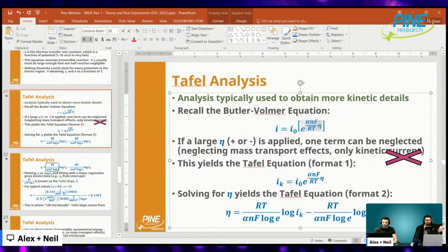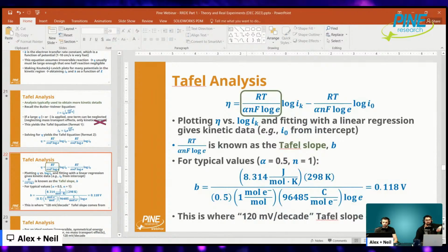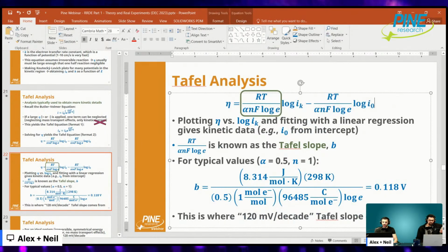Just do a manipulation, take the natural log of both sides, or the log base 10 of both sides, and we solve for eta, and then we get what's known as the Tafel equation, where we can get the Tafel slope. The Tafel slope is all of this stuff in the green box, RT over alpha NF log of e. This is just a number, okay? And this comes from the plot of the overpotential versus the log of, again, kinetic current. So again, I'll harp on this point until I'm blue in the face and I'm rolling over in my grave someday. Don't make a Tafel plot unless you know you have kinetic current. It's a common mistake people make: they take any voltammetry data, turn it into a Tafel plot, and assume it's valid. That is not an appropriate thing to do in a lot of cases.